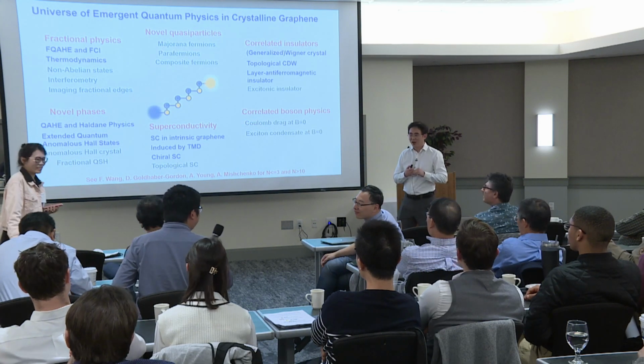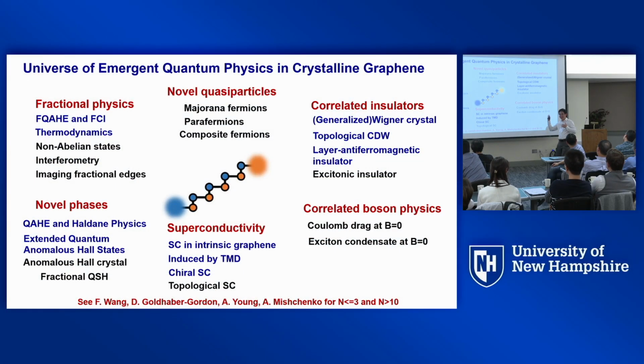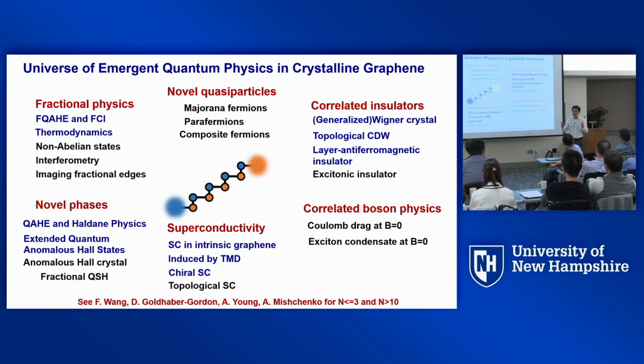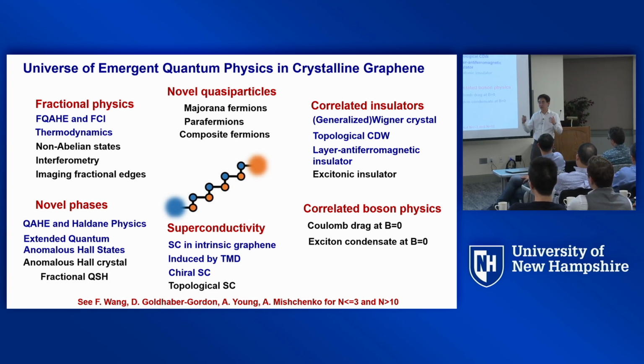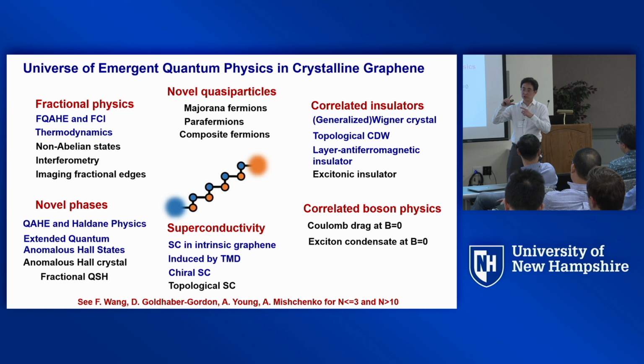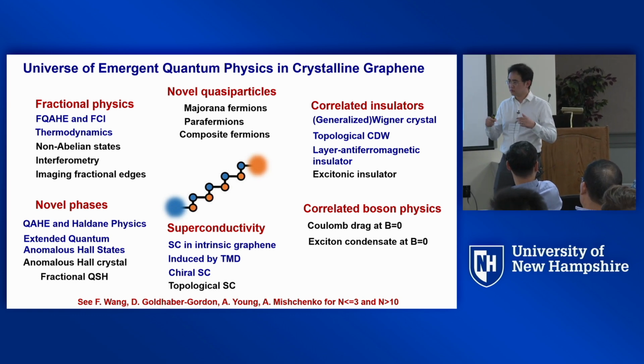I wish I could tell you that the thicker the better, but so far we have explored the 4-layer, 5-layer, 6-layer. These three are, in many senses, very similar. Fractional quantum anomalous Hall and maybe superconductivity in the phase diagram are very similar. I do not know exactly what happens if you go to much thicker than this, because I think Geim did some experiment back in 2020 showing 10-layer rhombohedral or thicker than 10-layer. The correlation effect there seems to be weaker than in this.